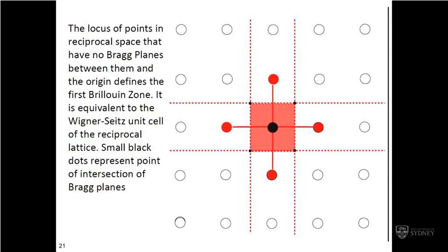And we are drawing it around the center black point. Remember, it was the shape that, for any position in this shape, it is closer to the center point than to any other of the lattice points. And remember the way we created it? We drew a line bisecting the nearest neighbor, and where all those lines intersect, that's the way you created the Wigner-Seitz cell.